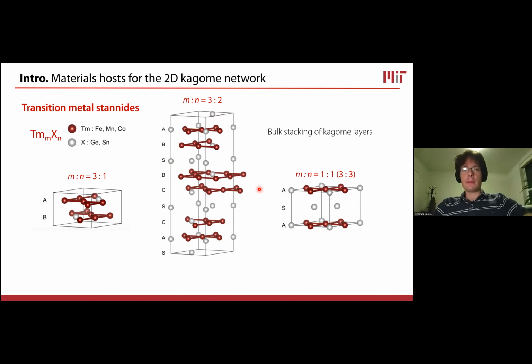And the first family of materials that we looked at is the family of transition metal stannides. And these materials come in different shapes and forms, and they have a fairly versatile stoichiometry where you can change the ratio between the transition metal and the metal. The transition metal can be anything like iron, manganese, cobalt, and the metal can be germanium, tin, indium. So there's quite some variety, both chemically and structurally.